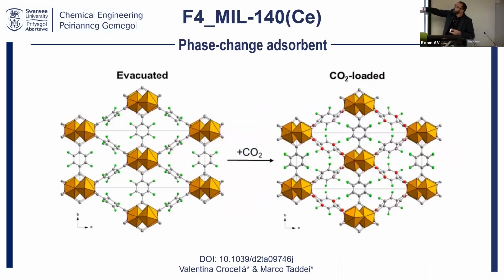This is work done by Marco Taddei. So this is not part of the project, but it was very important for me to show you. We still have the same linkers in blue, the same yellow, the same metal chain. And now these are our linkers. They are different from before because there are some fluorine atoms around this equator. So what happens here is when you expose this to CO2, those bending rings do a sort of dance. They all click at the same time, and you will see why it's so important.